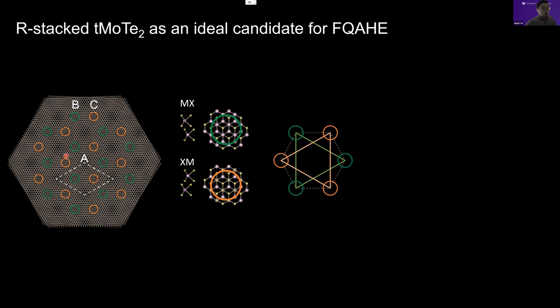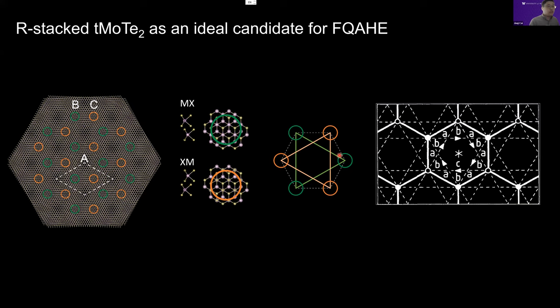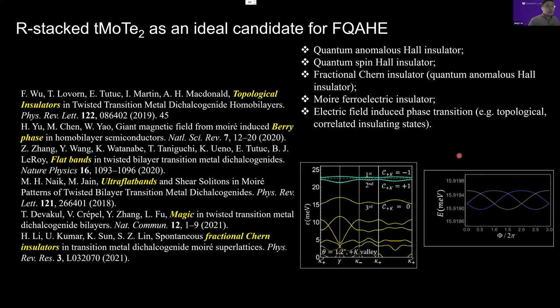If you look at the periodicity of this Moiré superlattice, it's actually a honeycomb lattice with complex nearest neighbor hopping and next nearest neighbor hopping. That is a very neat realization of what Haldane proposed 20 years ago, which is a honeycomb lattice with complex hopping that has a non-trivial topological band. After people learned about twisted TMD, there were lots of theoretical predictions of, for example, quantum anomalous Hall insulator, quantum spin Hall insulator, fractional Chern insulator, or Moiré ferroelectric insulator, and electric field induced phase transition.